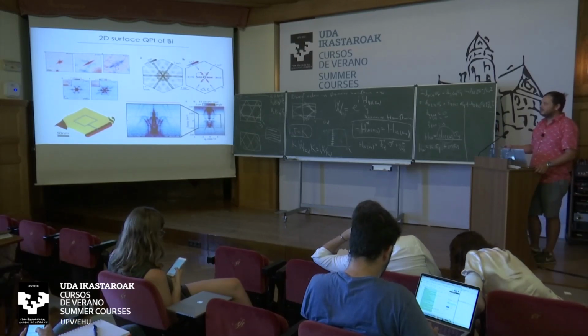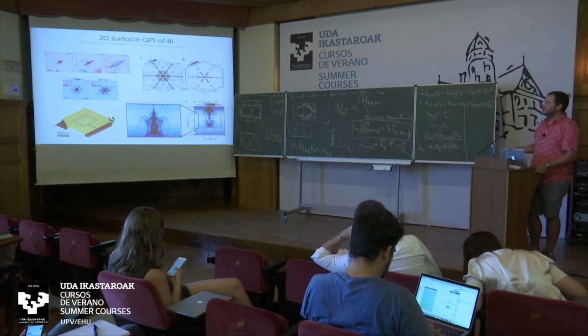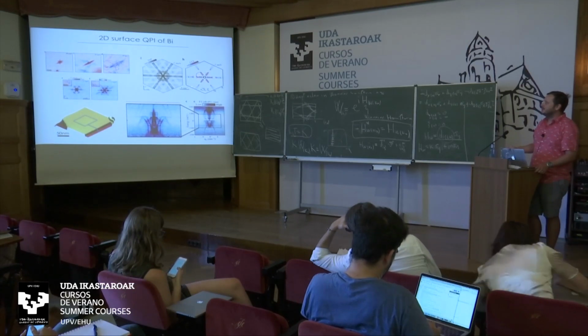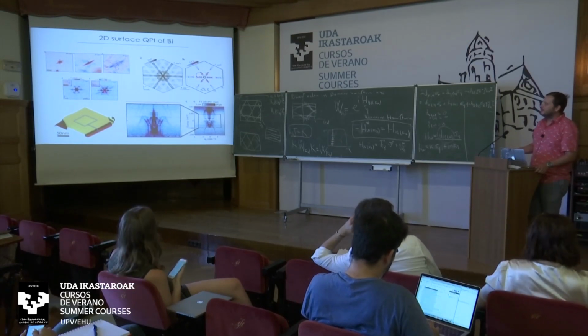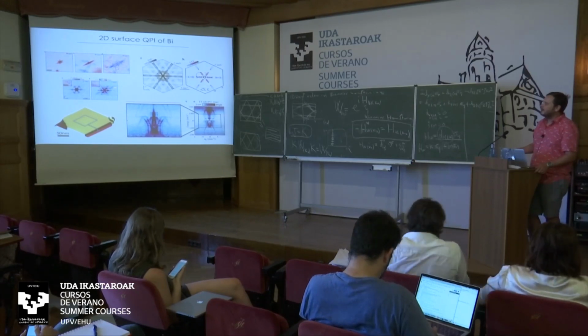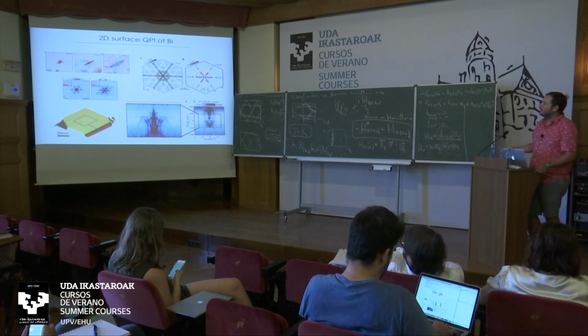So we can resolve almost, I should say, and I allude to in a minute why I say that, almost all the scattering processes that we see in the experiment, in the Fourier transform, to the different scattering processes. For example, this ellipse-like structure, maybe you can see them, are coming from scattering within this teardrop hole pockets.